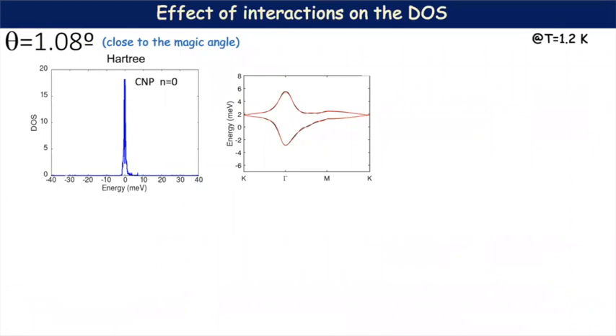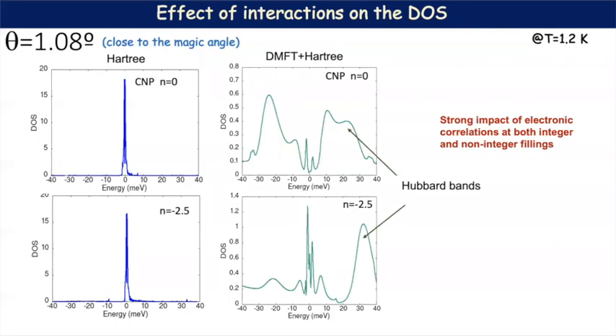And then as I turn on the interactions, you can see that there is a large impact of interaction on the density of state. On the right, I have the density of state with interaction from the DMFT plus Hartree calculation. And you can see that all the spectral weight from this huge Van Hove peak is now in these Hubbard bands. This not only happens at the integer fillings, but also at non-integer fillings. Now, let me show you this density of state for a continuous range of doping.